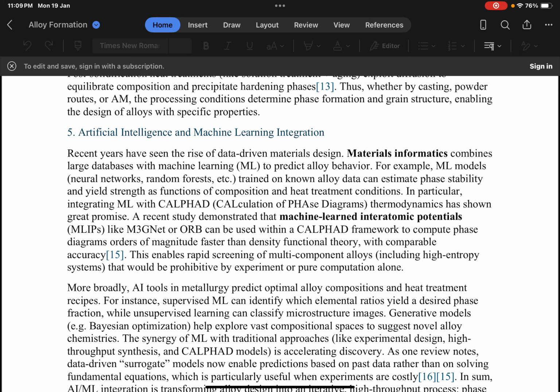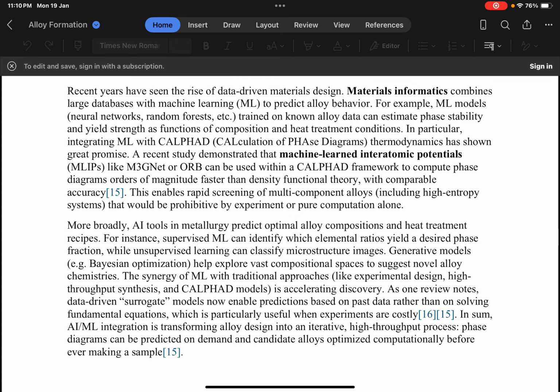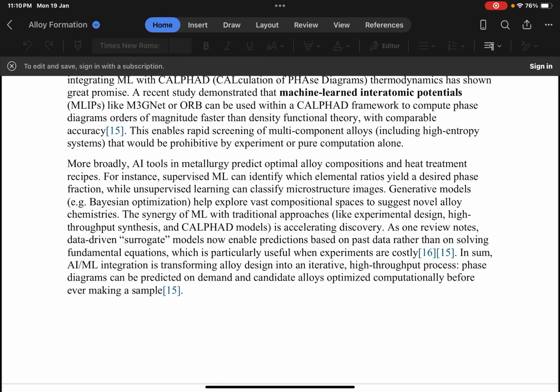In particular, integrating machine learning with CALPHAD calculation of phase diagram thermodynamics has shown great promise. A recent study demonstrated that machine-learned interatomic potentials like M3GNet or ORB can be used within a CALPHAD framework to compute phase diagrams orders of magnitude faster than density functional theory with comparable accuracy. This enables rapid screening of multi-component alloys, including high entropy systems, that would be prohibitive by experiment or pure computation alone. More broadly, AI tools in metallurgy predict optimal alloy compositions and heat treatment recipes.